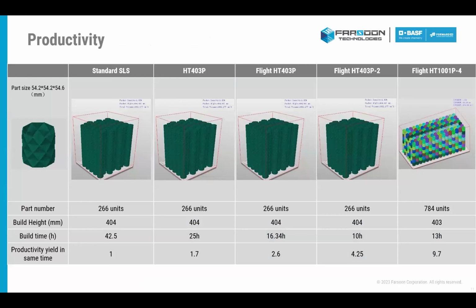So what does that all mean? So looking at productivity, we put into perspective the level of productivity that our flight system offers over traditional SLS technologies. We put together a full pack-out build of the same standard size parts in a standard SLS system that you may find out on the market, compared to our CO2 403 system, our single laser and dual laser Flight 403 systems, and then our quad laser 1001 flight system. So a standard CO2 laser SLS system with a full pack out of 266 parts will complete a build in about 42 hours, almost 2 days for a build, which is not ideal in a manufacturing type environment.